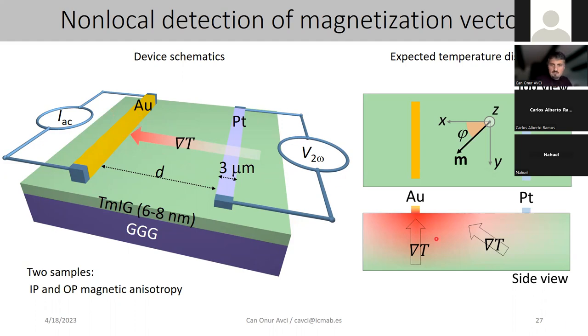This serves just to create the temperature gradient in the film. So the temperature gradient that we are expecting is that underneath the gold, you have a vertical temperature gradient, but underneath the platinum, you have a mixed temperature gradient. So we have an in-plane gradient and an out-of-plane gradient combined because of the three-dimensional dissipation of the heat.